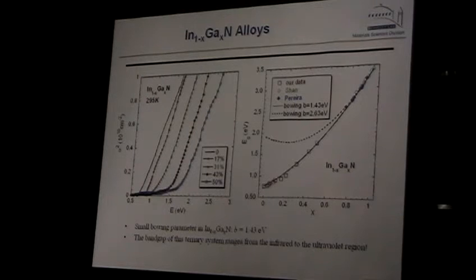And so now when we change the composition, we go from indium nitride, which has gap 0.7 electron volt, and we add more and more gallium, so the gap goes towards gallium nitride. You see that it spans a very large range of gaps, starting from 0.7 and going up to 3.4 electron volts. Previously, of course, people thought that it goes from 3.4 electron volts to 2 electron volts, but that has turned out to be completely wrong. So all of a sudden we covered the whole spectral range with material of different gaps.